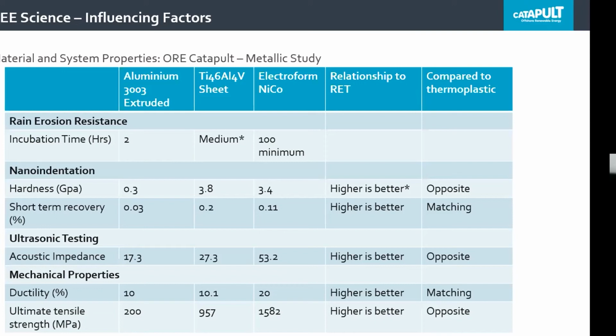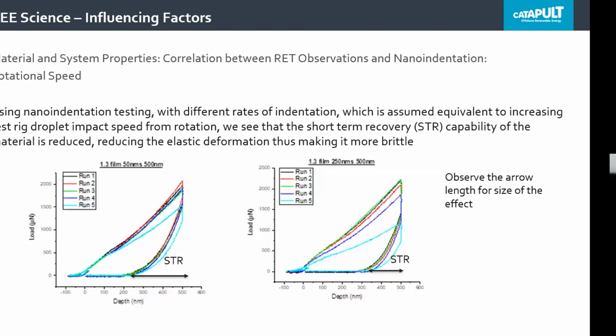So what I'm trying to show from this and conclude is that there's still a whole load of unknowns and lack of relationship between material properties and rain erosion resistance. Going back to the short-term recovery, what you can see is we've used nano indentation and found some correlation with short-term recovery and with what we actually observe in the rain erosion test rigs.